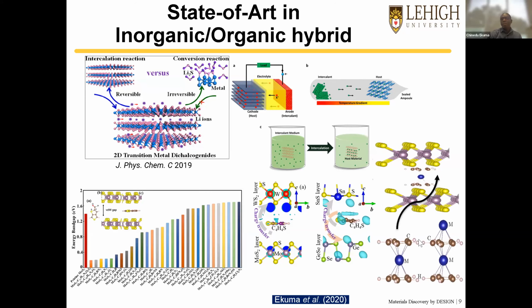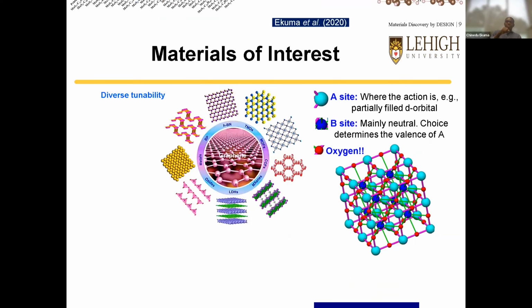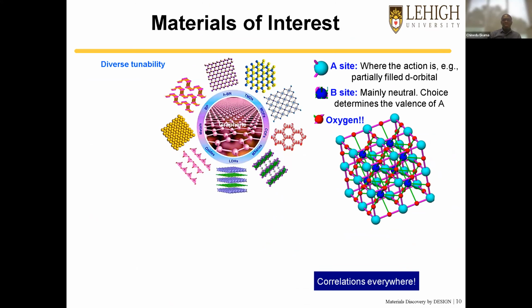And we can even go a little further by taking ring-like structures. This particular example are the so-called metallocenes. The metallocenes include ferrocene, cobaltocene, chromocene, and the rest of them. And we can insert them either vertically or horizontally within these natural van der Waals gaps. And that also gives us another lever to further tune the properties of the material. I'm just showing you the type of materials that we're generally interested in, mainly the whole 2D structures, and these are some of them. We've also been looking at perovskites, and not just only oxygen. We also look at halogens like chlorine, iodine, or bromine, replacing oxygen in these ABX3-like structures, and a couple of other complex perovskite-derived structures that I will share with you.